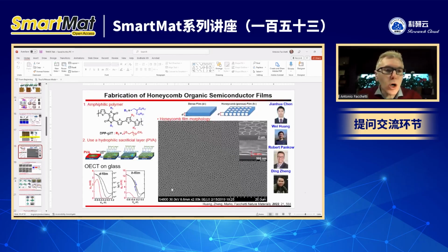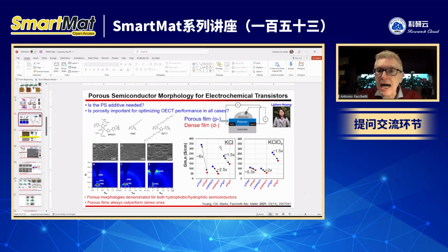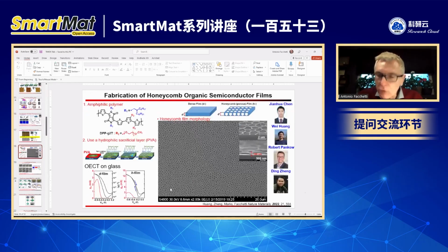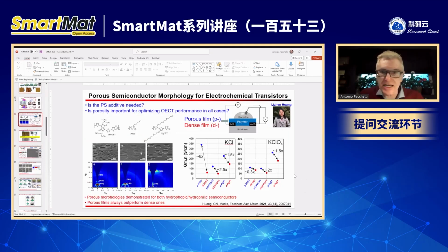Really, this is from a polymer organic. These are not very beautiful structures. These are not very good. And this is a really nice honeycomb structure with holes that go through, not just craters, really holes. There are two important aspects you need. First, you have to have a polymer which has both a hydrophobic chain and a hydrophilic chain. You need both. Also, what is most important is that all these films were fabricated on glass or on silicon oxide.